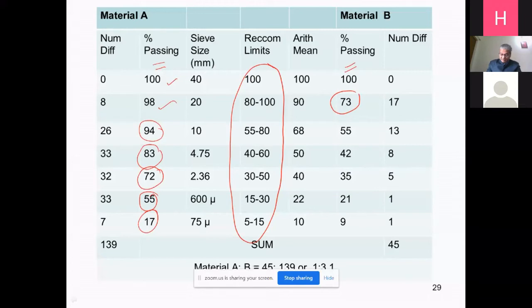So what you have to do is find out the midpoint of these recommended limits. For example, 80 to 100, the midpoint is 90. 55 to 80, midpoint is 68. 40 to 60, midpoint is 50. After that, you have to find out the numerical difference of A and B with the arithmetic mean of the recommended limit. For example, 90 minus 73, 17. 68 minus 55, 13. 50 minus 42, 8.